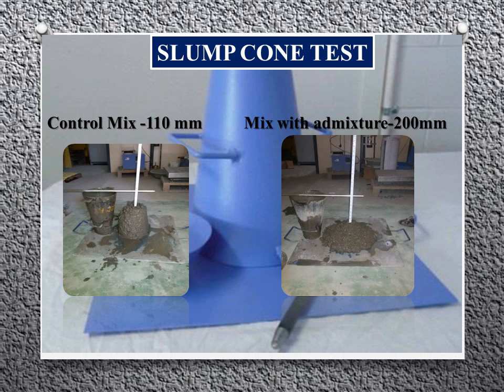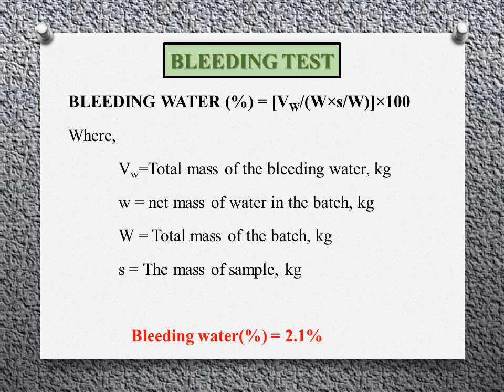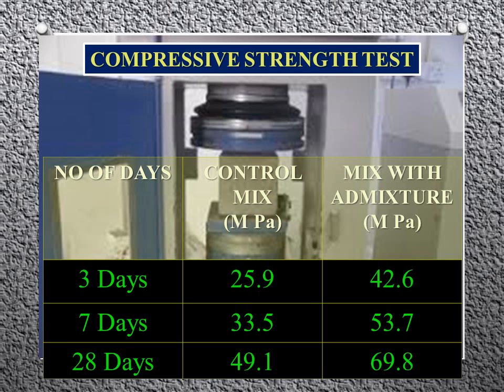The slump cone test, that is the workability test, carried out for the control mix gives 110 mm, and the value obtained for the mix with admixture is 200 mm. Bleeding test, which gives a 2.1% value for the bleeding water. The compressive strength test was carried out for various ages for both the control mix and the mix with admixture. Thus, from this tabulation, we can see the comparison, which shows that the mix with admixture shows a higher value.